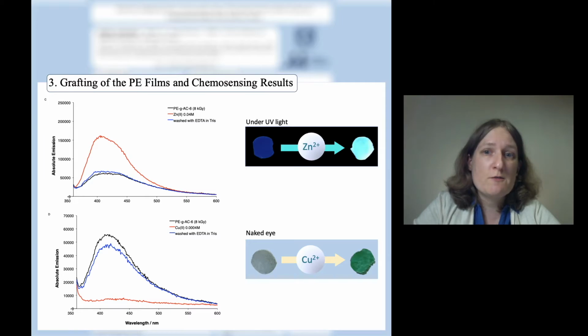The immersion of the film in a solution containing copper led to a decrease in the fluorescence emission. At the same time, a color change from transparent to green was observed by naked eye. The film could be washed with EDTA and reused several times.